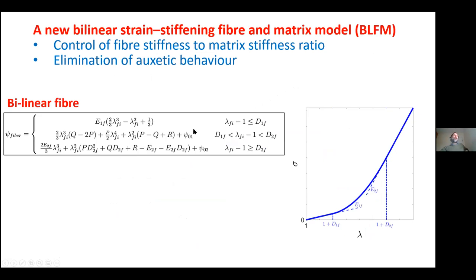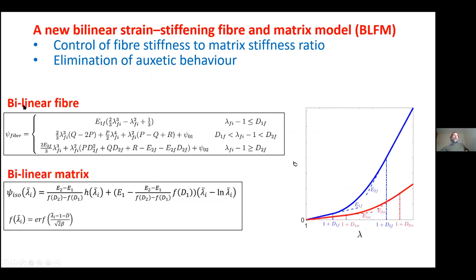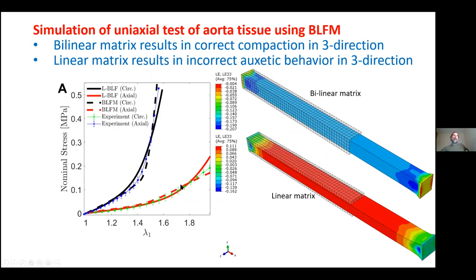So we proposed, in addition to a strain stiffening fiber, that we should also use a strain stiffening matrix material, where we control the stiffness of the matrix to increase as a certain proportion of the stiffness of the fiber. And when we do this, we get a very good representation of the material behavior.